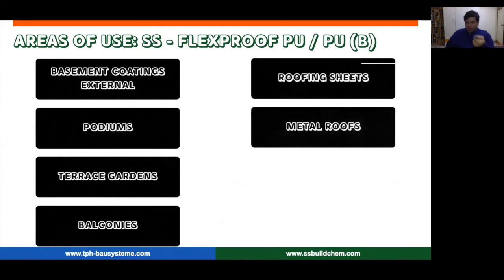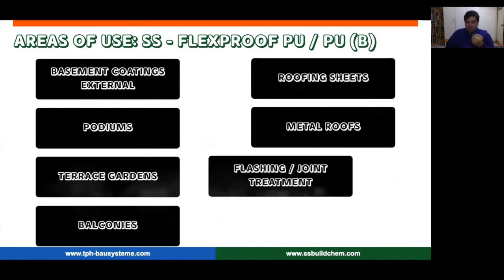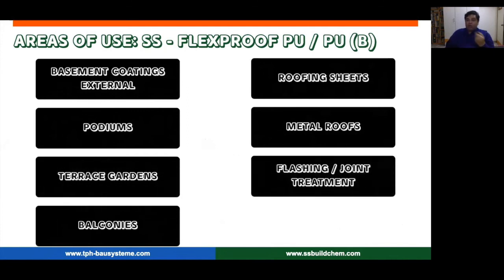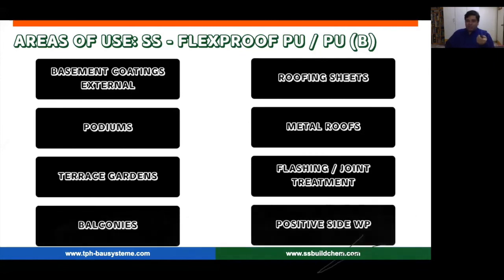The white one, or the PU one without the pitch, you can use for roofing sheets, for metal roofs, and you can also use it for flashing or joint treatment. So basically, when you use the coating along a coving, and you use a reinforcement system along with it, that holds the entire joint or transition system and waterproofs it very effectively. You can also use this as transitions between your masonry walls and your RCC structure.